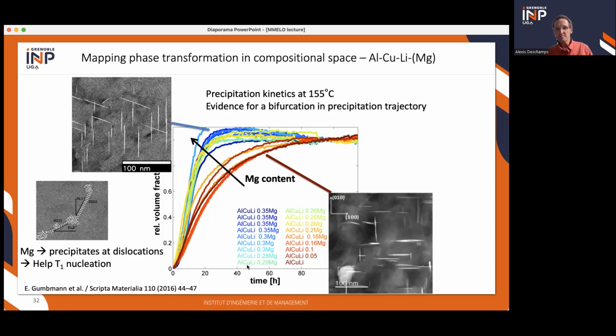So if you have less magnesium than 0.1%, you don't have enough supersaturation to form this kind of precursor of S phase. And this S phase participates to help nucleation of T1. So it's an indirect effect of a minor solute addition to help nucleation of an equilibrium phase. And you need a critical amount of solute addition to trigger this effect. And this can really only be characterized on a gradient. If you have only 2 or 3 compositions, you will just see by chance some evolution, but not have a full characterization of what happens in compositional space.